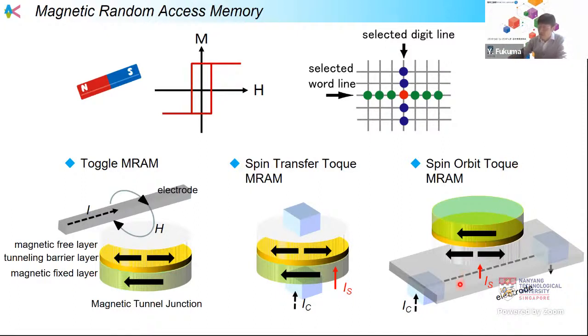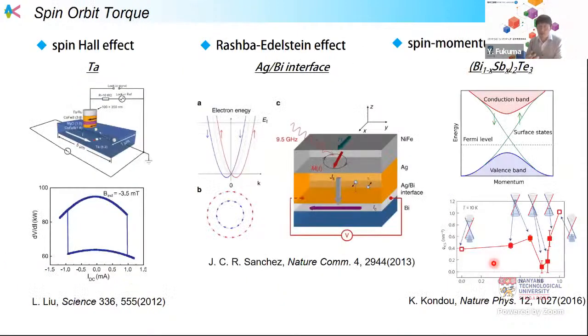In the case of spin orbit torque, when we apply the current along the electrode like this, then we can inject the spin current into the free layer. Then we can control the magnetization in the free layer. So how can we generate the spin current from the electrode? There are three main candidates: the spin Hall effect, the Rashba-Edelstein effect, and also the spin momentum locking state in topological insulators.